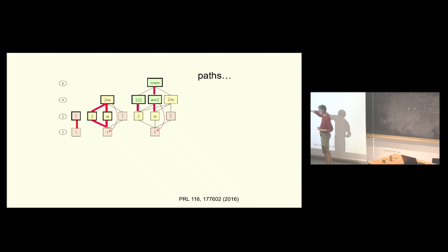if you have triclinic with inversion, you can decrease the symmetry to triclinic without inversion. This is the species, triclinic ones. Then these are all monoclinic groups, 2/m, m, and 2. And the species which starts from the monoclinic and goes to something lower symmetry, we call monoclinic species. So that's why in these plots I put it in a bold rectangle. I will show you later why it is important.